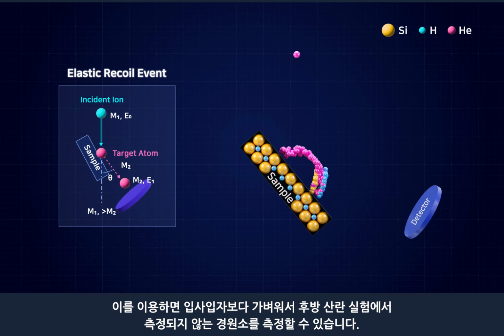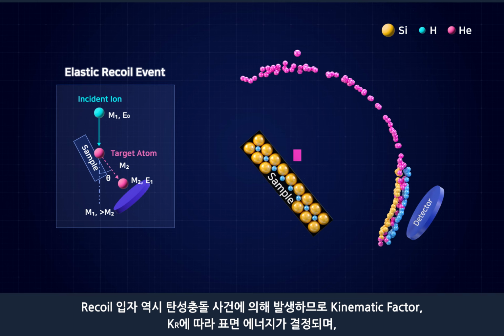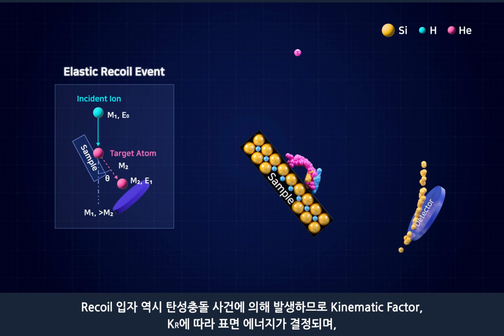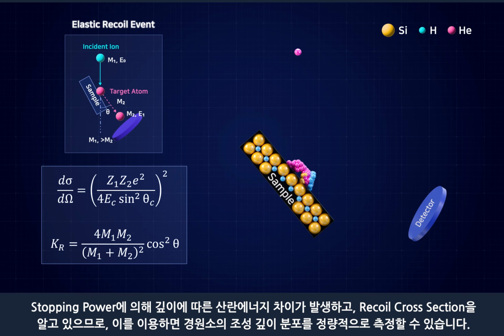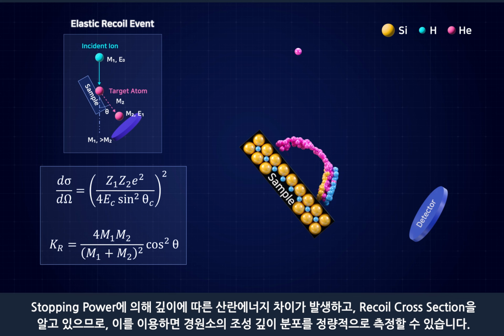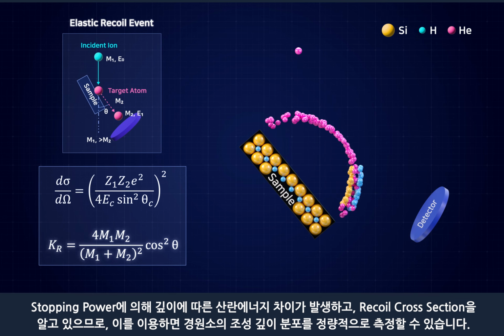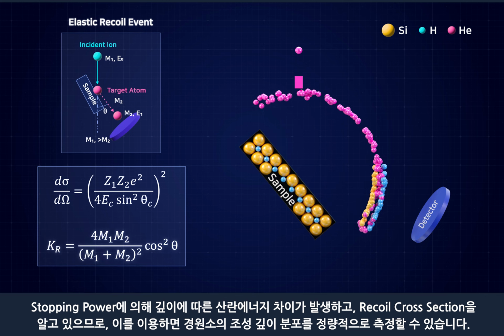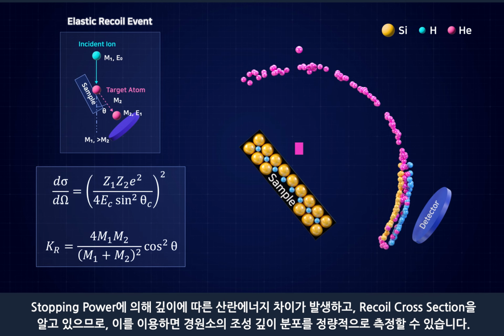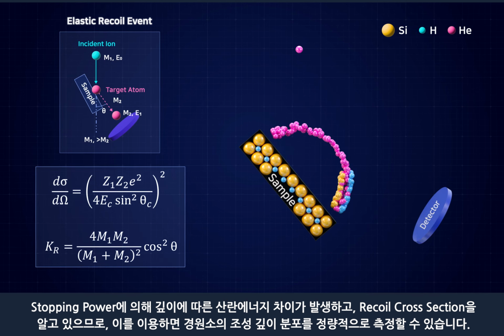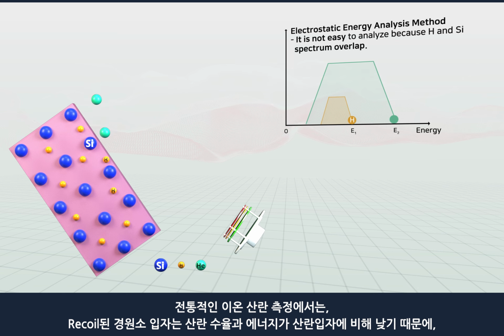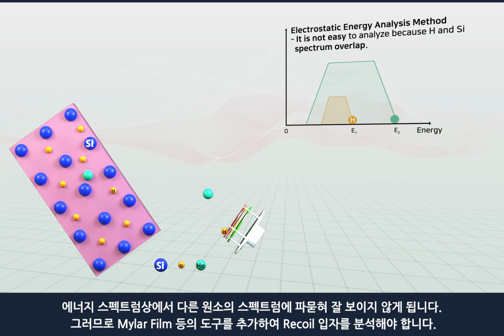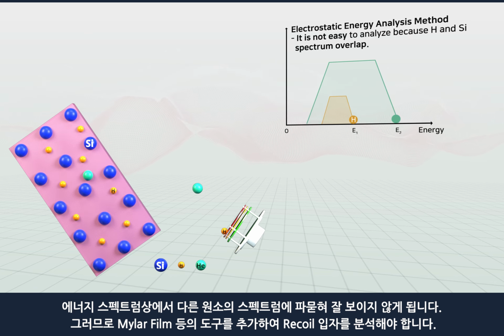Because recoil particles are also generated by elastic collision events, the surface energy is determined by the kinematic factor, K. The scattering energy is reduced as a function of depth by the stopping power, and the recoil cross-section is already well known. This can be used to measure the quantitative compositional depth distribution of lightweight atoms. The light element recoil particles have a low scattering yield, and their energy is also lower than that of the scattered particles. Hence, they are buried in the other spectrum of the energy spectrum and are not easily visible.